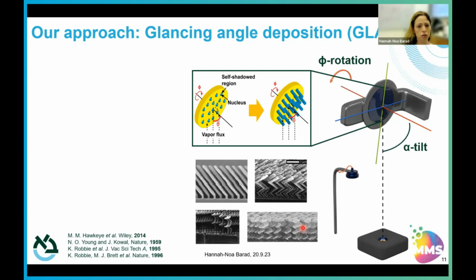So high control, it very much depends on the system. And generally speaking, this is done in E-beam because you can have a really large distance between your source material and your sample, which allows for vapor collimation, which improves the nanostructuring.